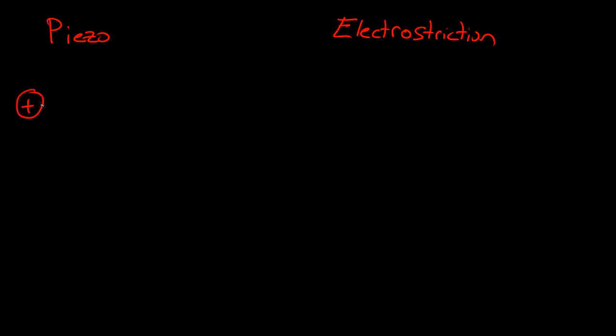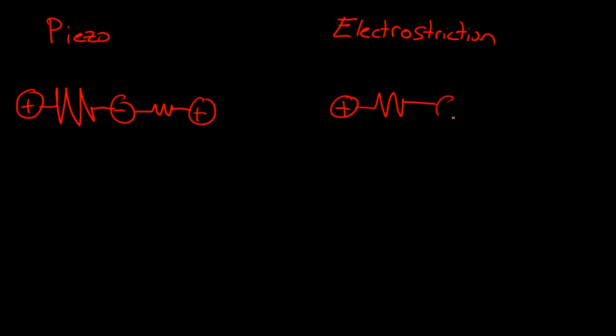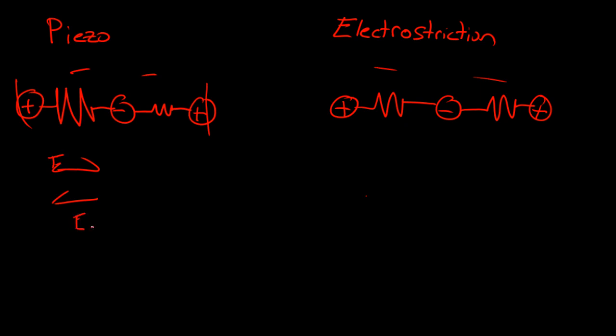We're just going to draw these little pictures of 1D materials, and we can understand quite a bit from them. In the piezo, we have a strong spring and we have a weak spring. In the electrostriction, we have the same spring. When you apply an electric field, depending on the sign, you will get a net displacement, because the stiff spring will pretty much not displace — delta L ≈ 0 — and this will displace.